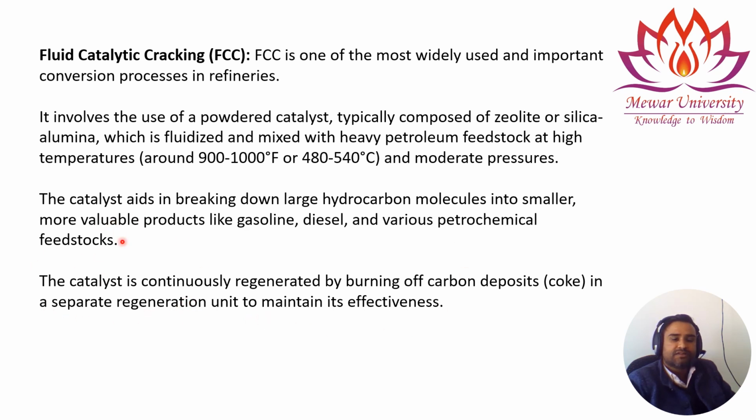So in fluid catalytic cracking, we are using the catalysts zeolite and silica. These catalysts are in powdered form, and they are fluidized and mixed with the feedstock at a temperature of 480 to 540 degrees centigrade. These catalysts assist in breaking down the hydrocarbon molecules into smaller, valuable products like gasoline, diesel and various petrochemical feedstocks like lighter naphtha. The catalyst is continuously regenerated by burning off carbon deposits, so it can be used again, and it is separated in the regeneration unit to maintain its effectiveness.